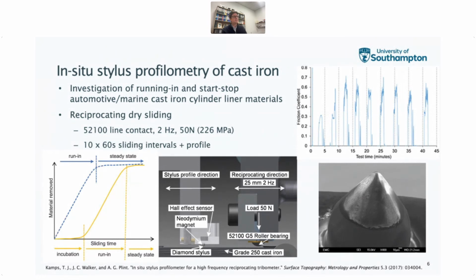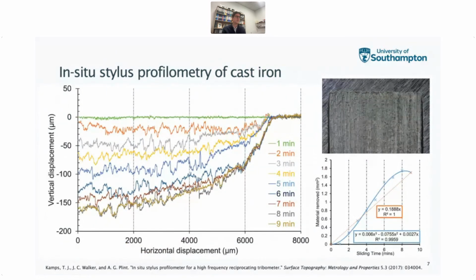And this is quite interesting, especially during the first minute of sliding, where we had a friction coefficient of 0.3, and that continued into the second minute of sliding, whereupon it increased to almost double that, 0.6, for the remainder of the test. And what we found from that was that we could quite nicely deduce the amount of material that was being removed in these minute intervals.